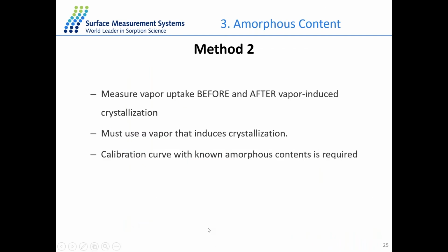And the next application related to pharmaceutical is the determination of the amorphous content. And we do have quite a lot of different methods for the amorphous content determination. And here I just want to introduce one very unique method we always apply, which is based on the crystallization point and the fact that the sample will squeeze out any kind of adsorbed molecules before and after the crystallization. So we just measure the uptake before and after the crystallization point.